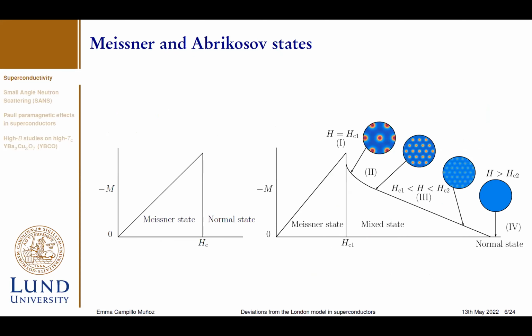So, as Sebastian explained before, essentially we have two types of superconductors. On the left-hand side, we have what we call type 1 superconductors. The particularity of these superconductors is that when we apply a magnetic field between 0 and a critical field, they are able to expel the magnetic field completely, which means that the material is able to create a magnetization which is equal and opposite to the magnetic field that we are applying to it. Then the magnetic field inside this material is 0. So that's why it's able to completely expel the magnetic field that we apply. And this effect is usually known as the Meissner state.